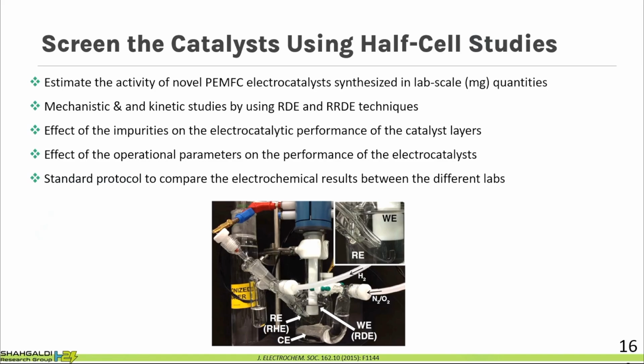So basically in our lab, when we produce a catalyst layer, or when we receive the catalyst from a company, the first step of screening is a half-cell study. We are not going directly to make the MEA to test it inside the fuel cell. We use a half-cell study to test the activity of the catalyst because it's faster and very cost-effective, and it gives us information about, for example, the activity of the catalyst that we produce or receive from industry compared to the commercial one. So we can somehow simulate the environment of a fuel cell and electrolyzer.